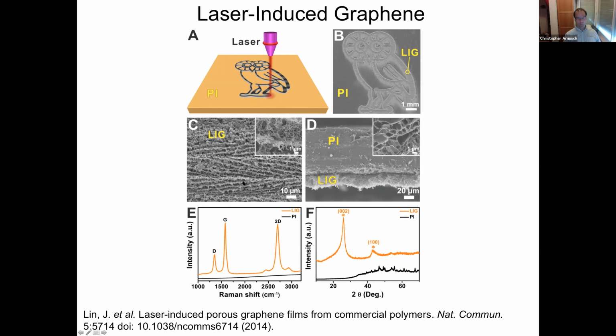And this picture is an electron microscope picture from the top, where you can see it's a very porous substrate. It's very electrically conductive and porous. This is a side view where you see the polyimide substrate and the LIG. So you can see that it is very thick, from 20 micron and up. We can get even 50 micron layers, 100 micron layers. So compared with the single atom graphene sheet, it's a very different material, so it can be used in many different types of applications.